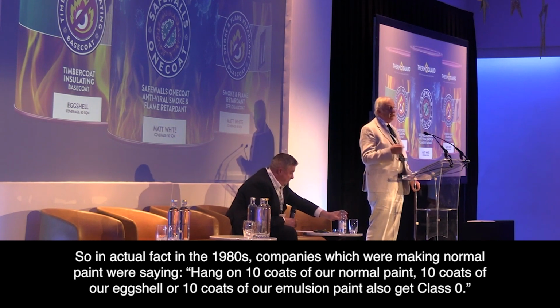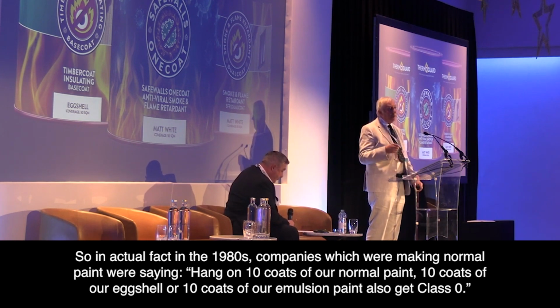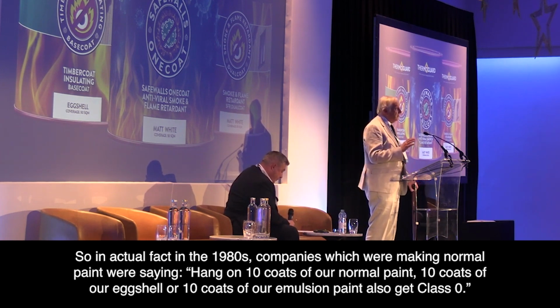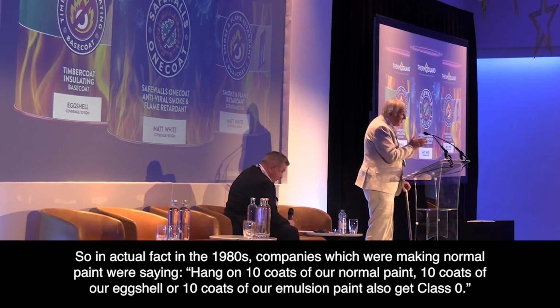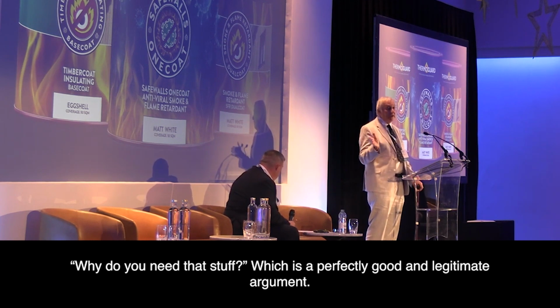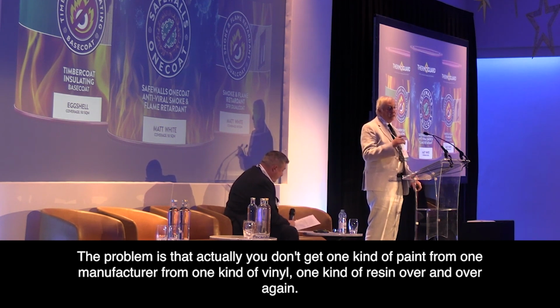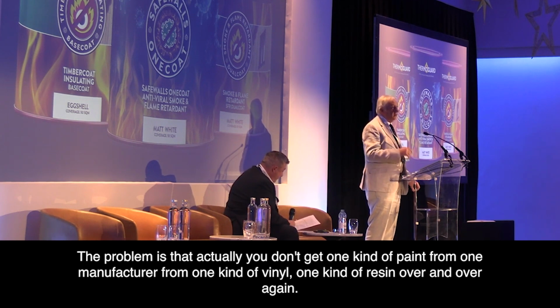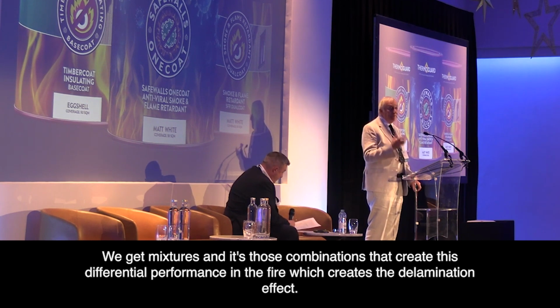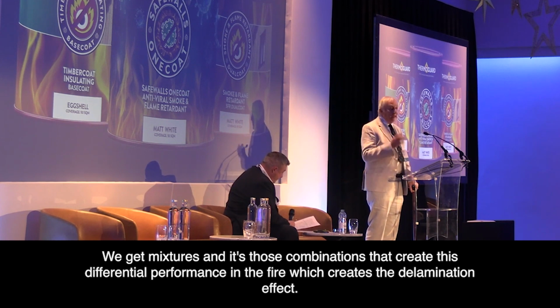In actual fact, in the 1980s, I've been in the game quite a long time, companies which were making normal paint were saying, well, hang on, 10 coats of our normal eggshell, or 10 coats of our emulsion paint, also get Class 0. Why do you need that stuff? Which is a perfectly good and legitimate argument. The problem is that you don't get one kind of paint from one manufacturer, one kind of vinyl, one kind of resin over and over again. You get mixtures. And it's those combinations that create this differential performance in the fire, which creates the delamination effect. So that isn't actually the risk.